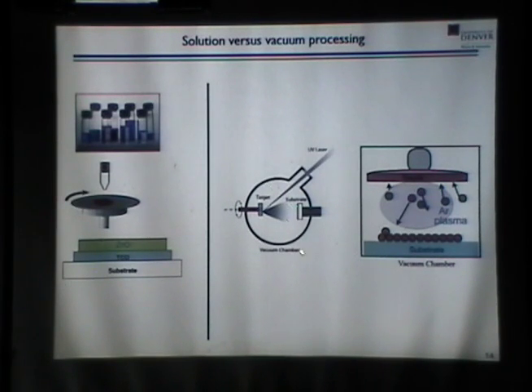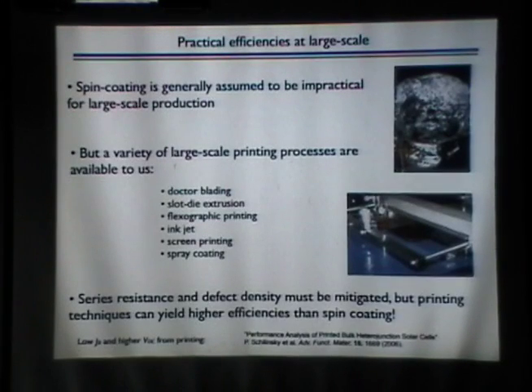So we have these two worlds for fabrication. We think this one is maybe a little cheaper. This one is probably a little better in terms of material purity and gives you some freedom in terms of how many layers you can put on top of each other. The issue with solution casting is that it's difficult to put a second layer on top of a first layer because you could wash away the first layer. So you need to be very careful about the chemistry to have orthogonal solvents to allow you to build up layers. Okay, so as I said, mainly I'll talk about this technology in the next couple of days, but all the physics I describe are equally valid for the vacuum processing side of things.